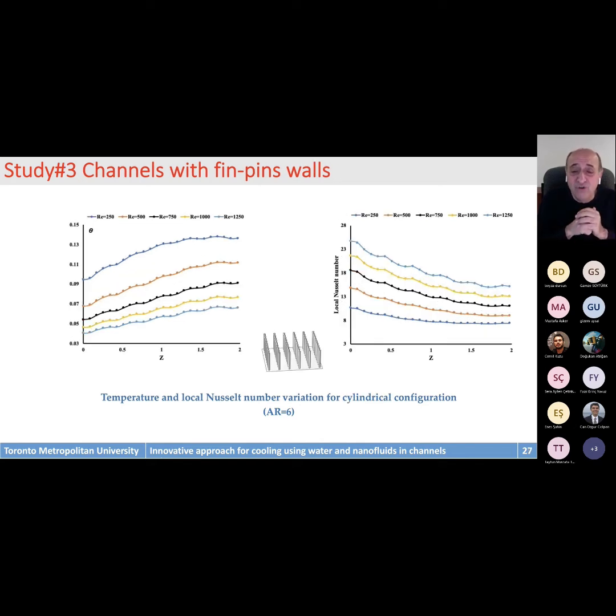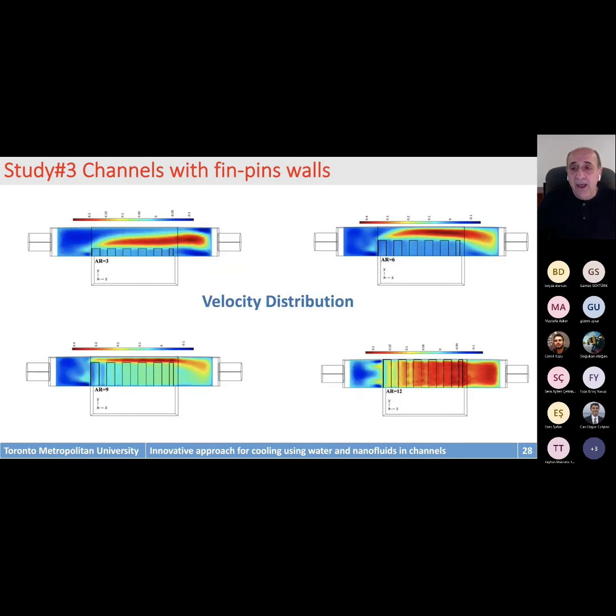We also did it for a circular pin fin, and the idea behind the circular pin fin versus the rectangular is that with the rectangular pin fin, you create more friction. And by creating more friction, we may have a higher pressure drop than for a circular pin, because flow around a circular obstacle has lower friction, therefore lower pressure drop. And one thing we did in this study, we varied the height.